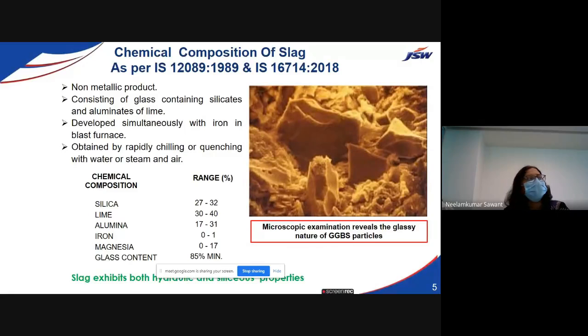We can see it's a non-metallic product. It consists of silicates and aluminates of lime developed simultaneously with iron in the blast furnace, obtained by rapidly chilling or quenching with water or steam in air. Silica percentage is 27 to 32. The best part is this slag is equal to hydraulic cement because of the calcium oxide, the lime content, which is approximately 30 to 40%. If slag is compared with fly ash, you will see that the calcium oxide percentage in fly ash is less than 3, whereas in GGBS, it is in the range of 30 to 40%.